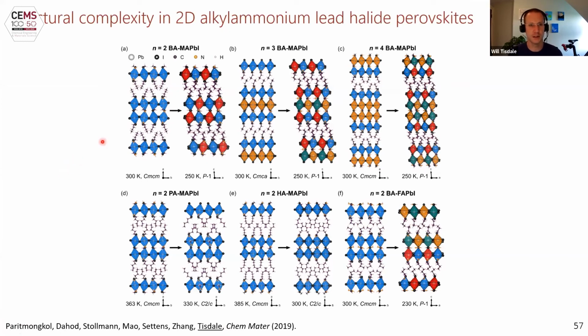What you can see in a lot of these crystal structures is that the halide octahedra are distorted. They tend to be tilted. It's rarely a purely cubic phase. There's lots of distortion of the halide octahedral network, and that's all determined by the steric hindrance of the organic cations that are bound to it.